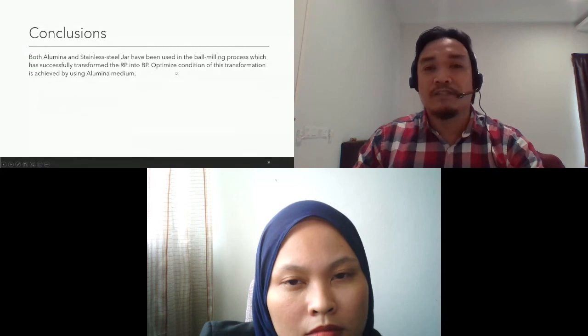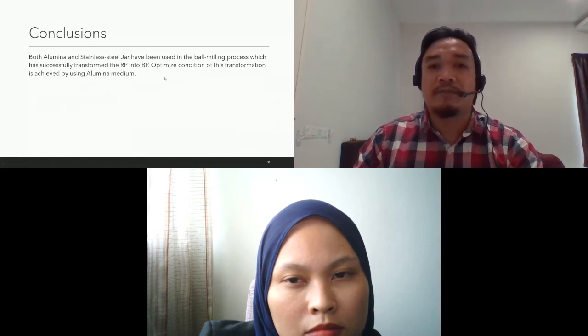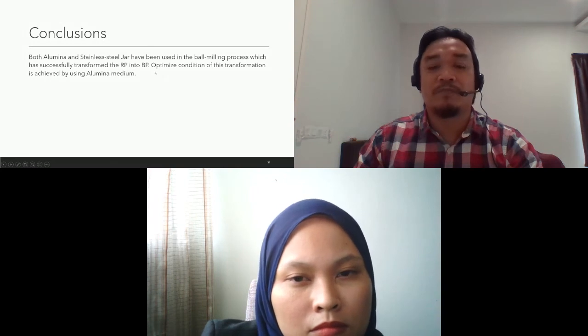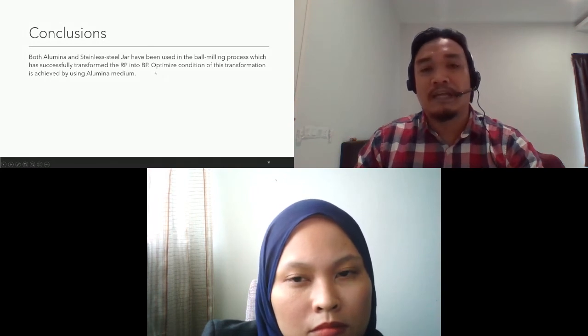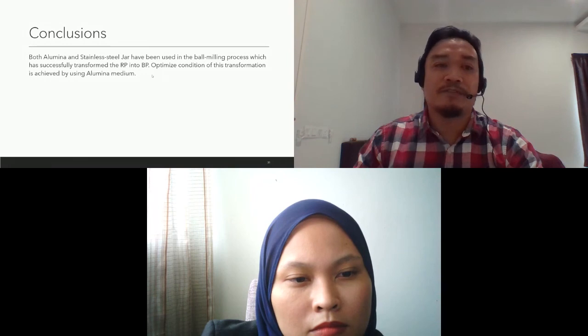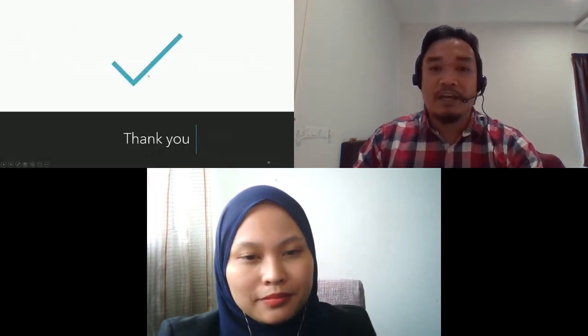So, conclusions for my work here: I found that alumina and stainless steel have been used to successfully transform the RP into BP, and the optimal condition of this transformation is achieved by using alumina medium. Okay, that's all. Thank you.